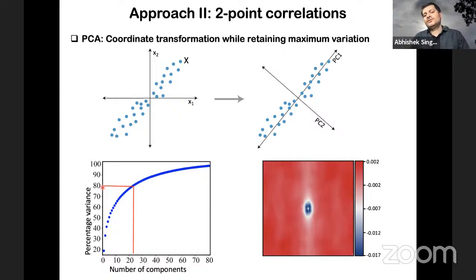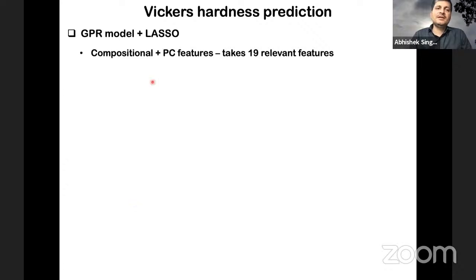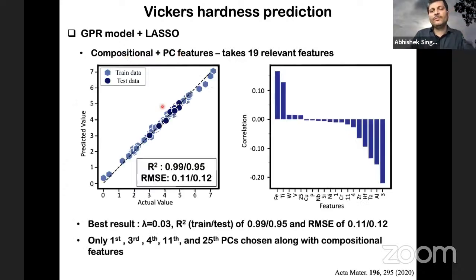Of course, as I told you, there could be as many PCs as the number of pixels. In this case, it was 40,000. However, only 80 were good enough to capture the variance. So we picked these 80, and on top of that, we applied the lasso to reduce it further. Then we added compositional features and PC features, just two types of features, and we get a very strong and very nice model, about 0.11, 0.12 RMSE, and 99% R square.